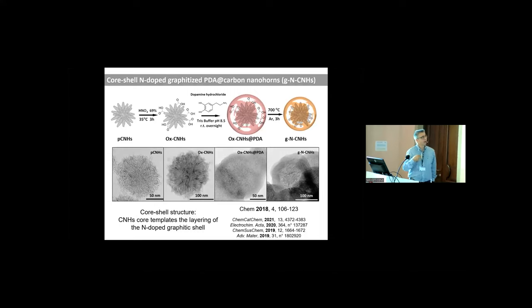Among the many materials which are under investigation in our lab, I want to mention nitrogen-doped carbons for electrochemical application. The first example is the use of carbon nanohorns with polydopamine thermal treatments to induce the formation of nitrogen functionalized carbon nanohorns that have been shown to be very, very active in hydrogen peroxide production. Very low overpotential, very cheap materials. Of course, probably this is a fancy starting material, but we have been investigating different syntheses of this material, even starting from very cheap components. In some cases, we use some metal nanoparticles as templating to obtain peculiar structure.